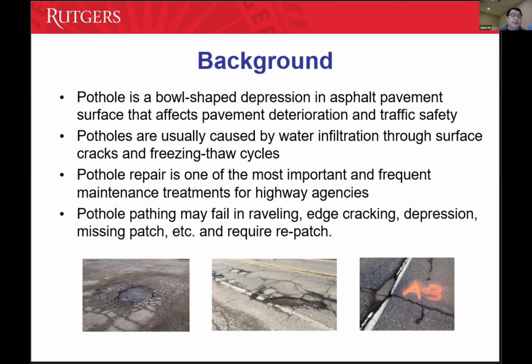That's also challenging. Another thing is, even if you repair the pothole, you may do an asphalt overlay on top of that. In this case, you also have some potential for reflective cracking. So if we can increase the longevity of repair, it will really save cost and also improve efficiency. If you look at the failure of pothole repair, it may have raveling, edge cracking between the repair and other areas, depression of the patch itself, and eventually a missing patch. And in this case, we'll do the repair again.